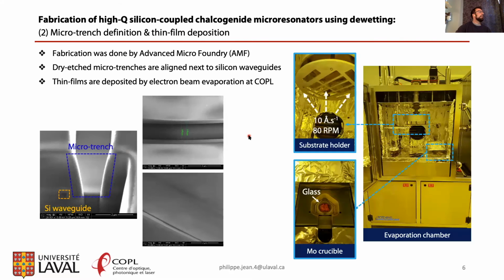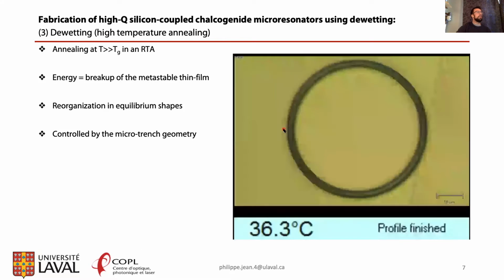Okay, so here you can see SEM images of the fabricated microtrench, where you can see the silicon waveguide right next to the relatively large microtrench that will be filled afterwards with chalcogenide glass. We do that using electron beam evaporation. Here you can see the evaporation chamber with the glass and the substrate holder that was rotated at 80 RPM. The deposition rate was 10 angstrom per second.